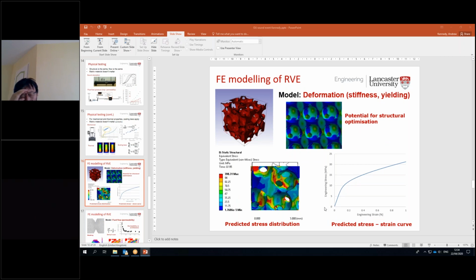Then, of course, there's important elements around the FE modelling. Here's some examples of meshing and modelling of mechanical performance of these porous structures, typically looking at stress distributions and predicting stress-strain curves from them, usually the early stages of them. When you get to high strains, it becomes very, very difficult. But it's clear that from these type of responses, particularly for ordered structures, you can apply inbuilt systems within things like ANSYS to do structural or topological optimization, to do further improvements of your modeling designs to make them more structurally efficient from a mechanical perspective.